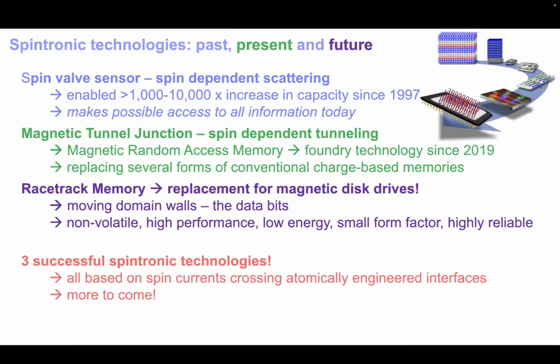And basically, I've spent too much time telling you about spin valve sensors, which are based on spin-dependent scattering, and magnetic tunnel junctions, which are based on spin-dependent tunneling. Spin valve sensors are used in the resistive form or in the tunneling form today in magnetic disk drives and enabled, roughly speaking, a 10,000-fold increase in the storage capacity of magnetic disk drives, so that 70% of all digital data is stored there. A magnetic tunnel junction we first proposed in 1995 could be a very interesting memory, magnetic non-volatile memory, and it finally became such a foundry technology 5 years ago.